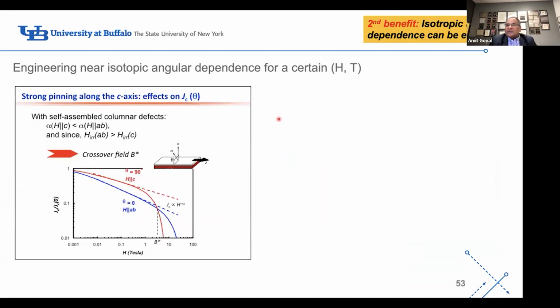Second, it allows us to create isotropic angular dependence. And the reason why that happens is when you plot the critical current density as a function of field along two orientations, H parallel to C and H parallel to AB.